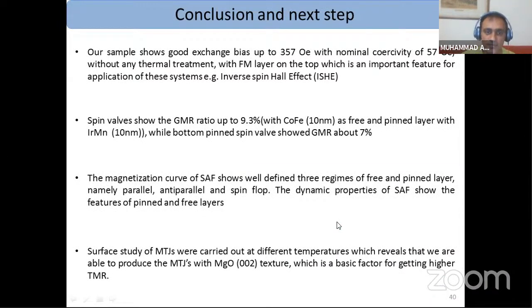In conclusion, our sample shows good exchange bias with nominal coercivity without any thermal treatment, with the ferromagnetic layer on the top, which is an important feature for the application of this system in spin Hall, inverse spin Hall effect. Our spin valve shows the GMR ratio up to 9.3%, while the bottom pinned spin valve shows the GMR about 7% with annealing.